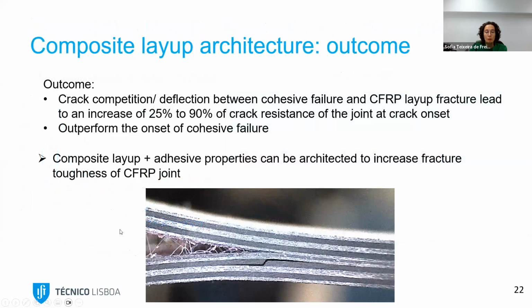So what are the outcomes of this sub-study that we have to perform? So crack competition and crack deflection between the cohesive failure and CFRP layup led to an increase of 25 to 90% of the crack resistance of the joint, because indeed the energy is being spent in different locations, and it can outperform the onset damage initiation of the cohesive failure.